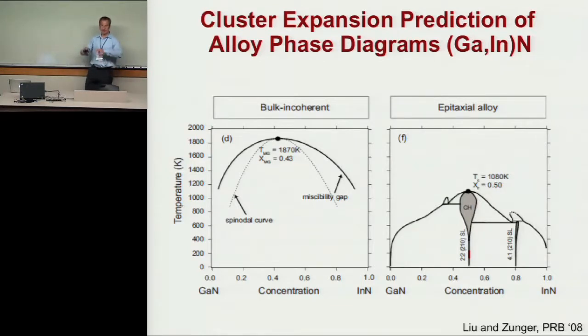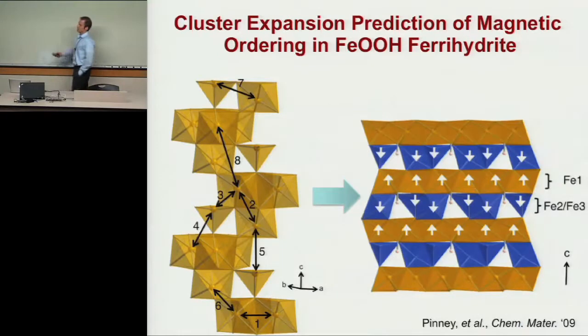And this can be a reasonably hard experiment to do. But people do begin to see ordering in epitaxial systems of this. And you can get at this thermodynamics by looking at how your energetics changes with ab initio when you force coherency and epitaxy, and then fitting these interactions and doing Monte Carlo to construct these phase diagrams. Some more work that we did.